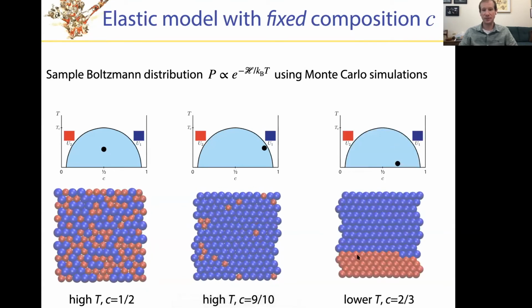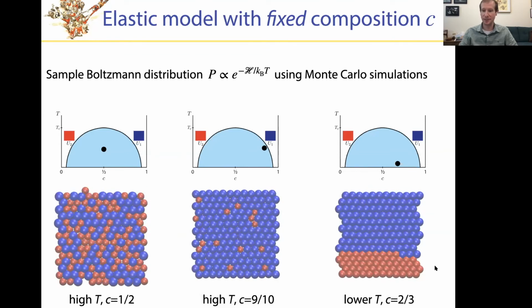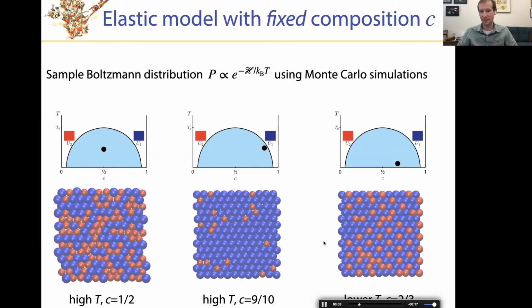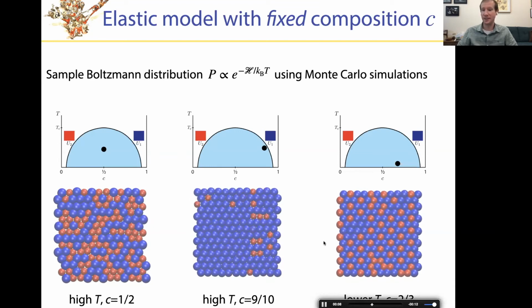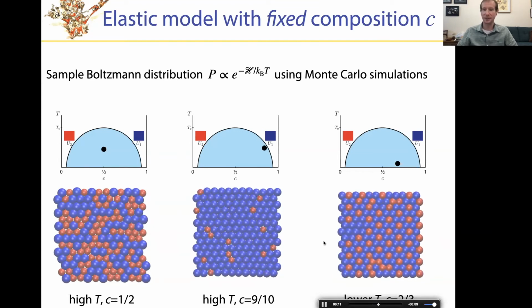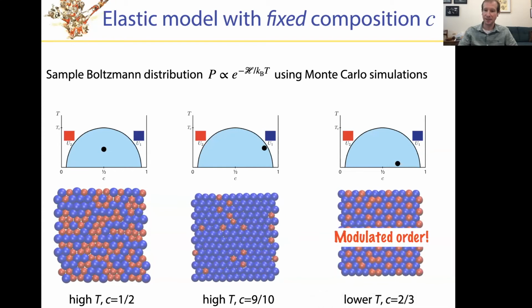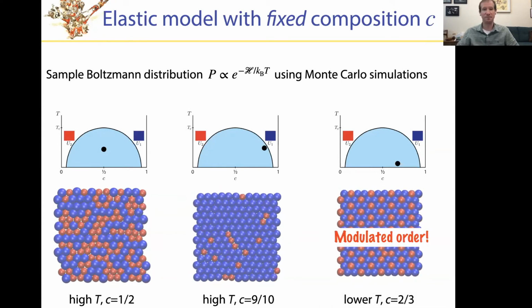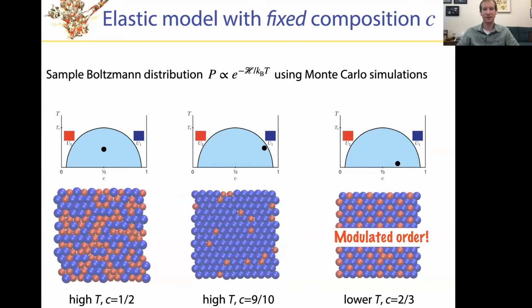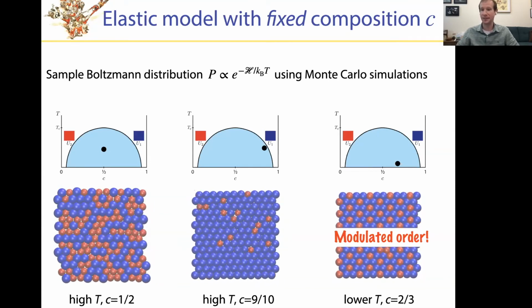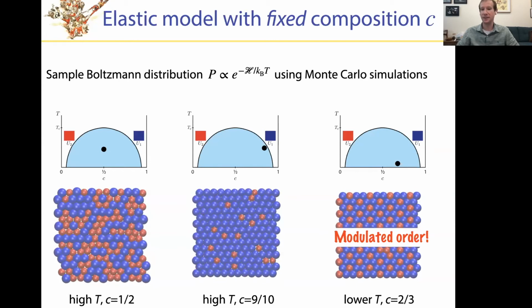So now let's go to a lower temperature and let's try and help it out by starting with a phase separated state and see what happens. And as time progresses, we find not only do these materials mix, but they mix in an intimate and a spatially ordered way. So we've discovered here the existence of modulated order, an exotic phase behavior that emerged from a very simple description of generic features of materials that are mixed in the way that nanocrystals must be mixed in the process of cation exchange.